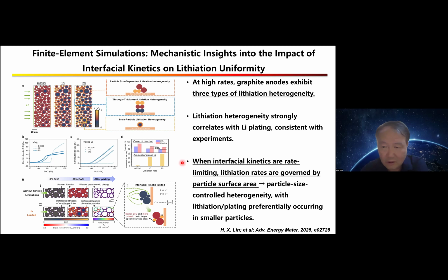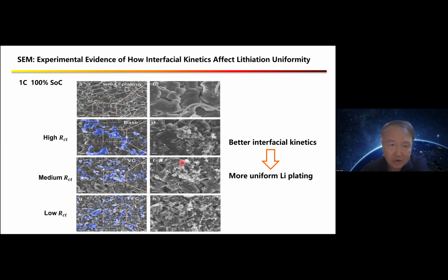We also checked different SEM images to observe the formation of lithium plating. You can see that with FEC additives, the lithium plating is more uniform, but with high charge transfer resistance, as in the baseline electrolyte case, you see larger lithium plating. Better interfacial kinetics cause more uniform lithium plating.